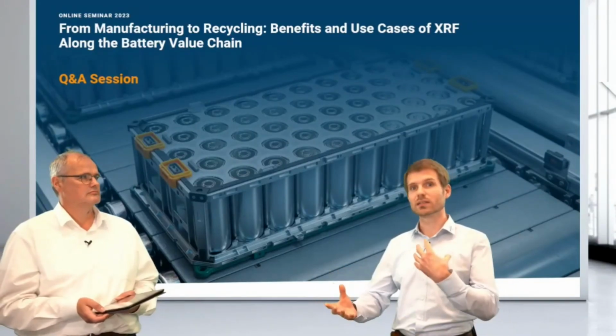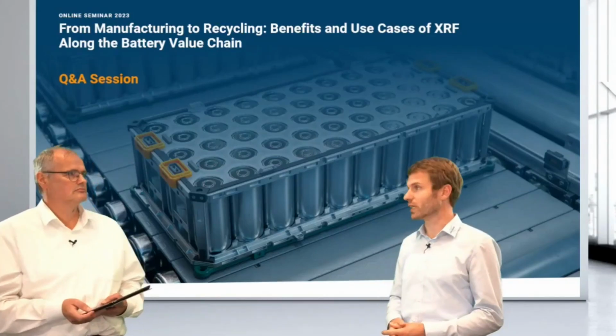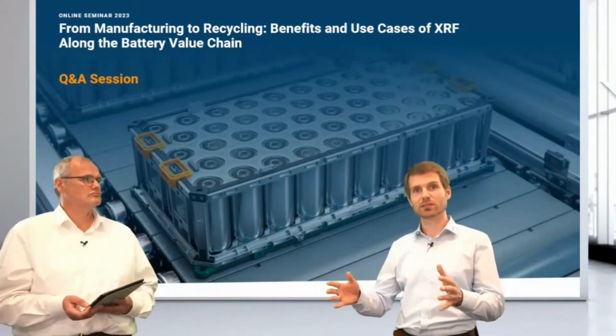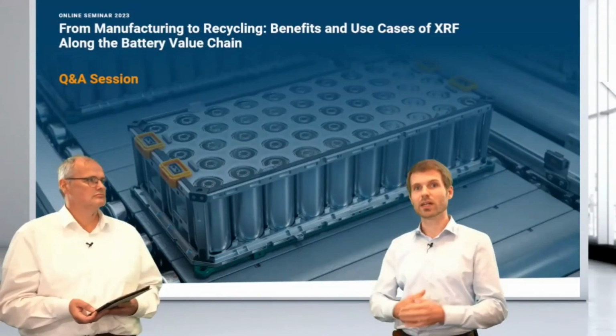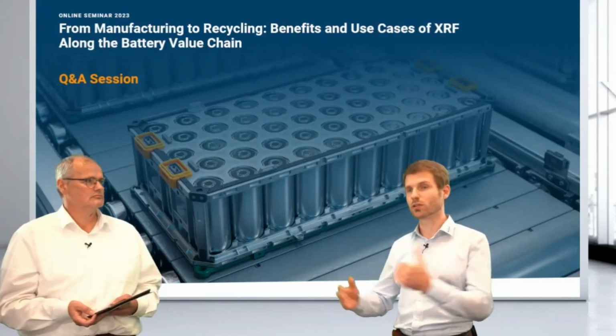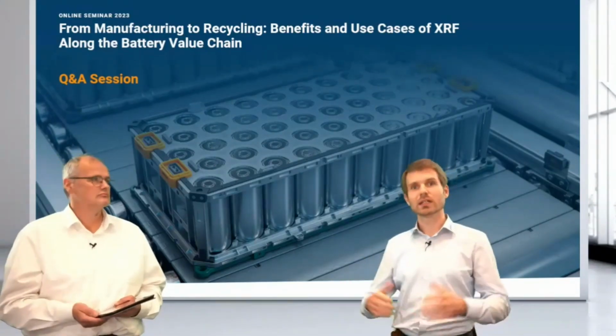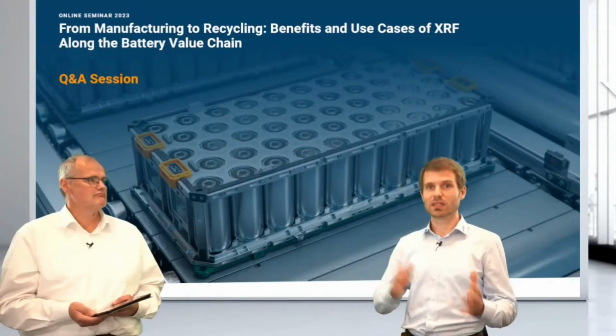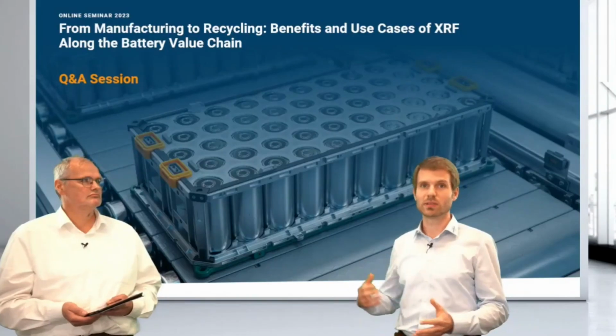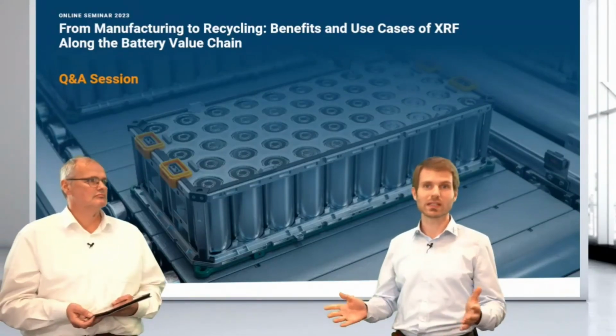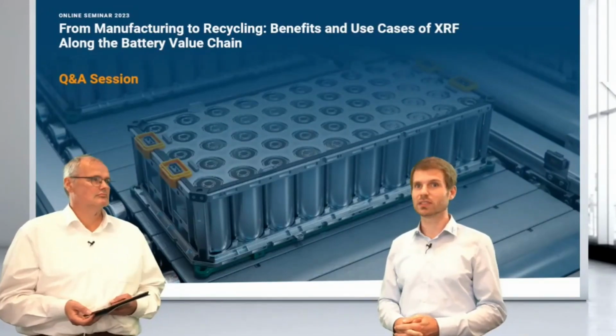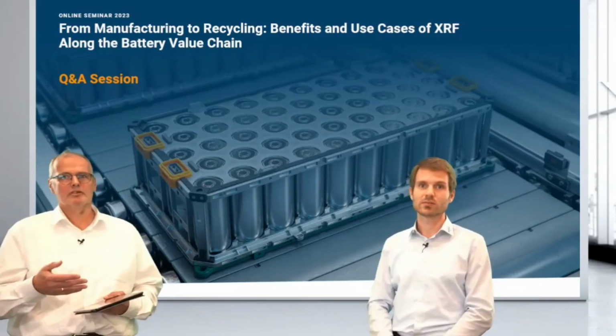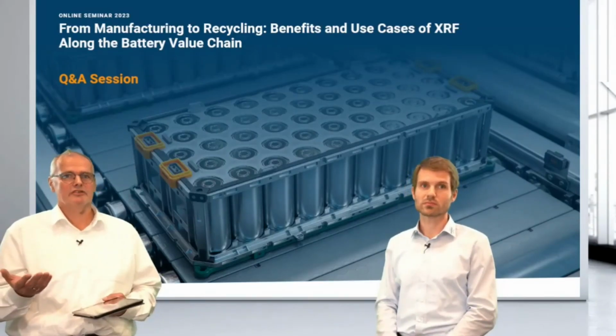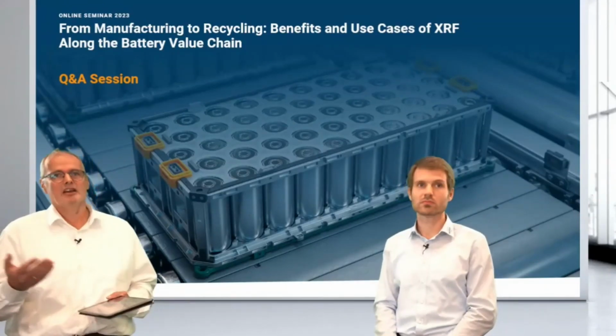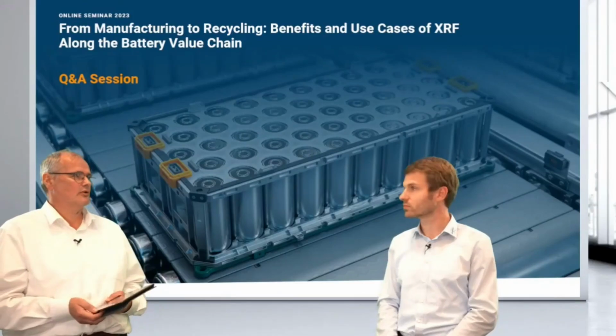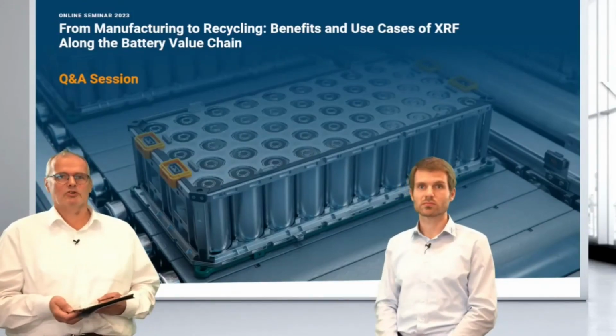The point is how reproducible your grain size is. If it's a really wide spread, sometimes more coarse, sometimes finer, then we would recommend to put it to a common ground, so basically grind it. The materials we've come across so far, maybe black mass recycled or precursor material, are typically suitable as is. So there we haven't come across many challenges with the grain size. When we have a very good material, we are at a range of 0.05% relative at best. It might be slightly less accurate for major elements the moment the material is coarser.